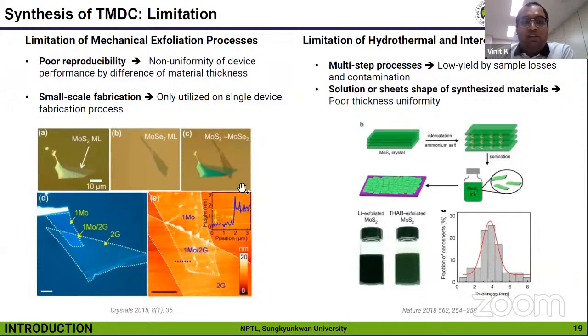So what are the limitations of these processes? First is mechanical exfoliation. The first problem is poor reproducibility, because, as I already told you, when exfoliating from bulk material, we cannot always get a monolayer or bilayer. We have to find them. The controllability of mechanical exfoliation is very low, and it is small scale fabrication. You will get only a small area of our TMDC material.